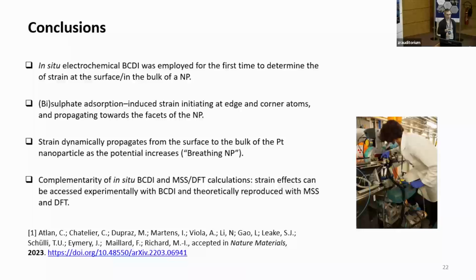Yeah, great work. I have a short question. You measure only one tensor component of the strain. So now when you see some strain, this could be either because the unit cell really contracts, or because it compresses in one direction and expands perpendicular to that. So the first question: is there some way to measure all tensor components of the strain? And second, of course, is there a chance to expand it into the range of platinum oxidation?